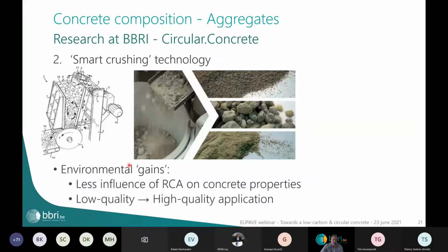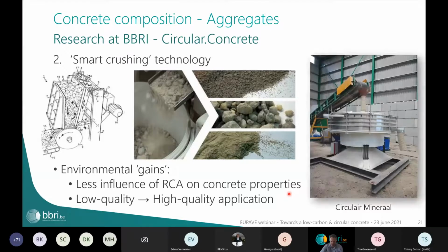The environmental gains are, of course, that the negative influence on the concrete properties of the recycled concrete aggregates due to the attached mortar on the aggregates can be lessened, and so to push perhaps a low quality application of a certain batch of recycled aggregates to a high quality application, just to improve the properties of these aggregates. So we did some experiments, and we went to Circulair Mineraal, which is a firm in the Netherlands, which has such an installation to produce these kinds of aggregates.